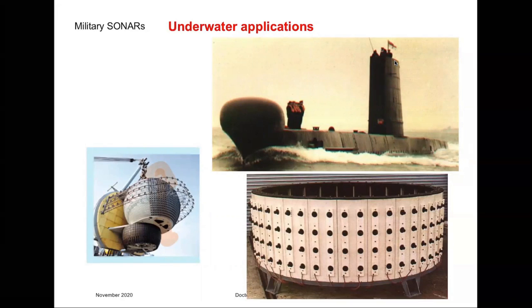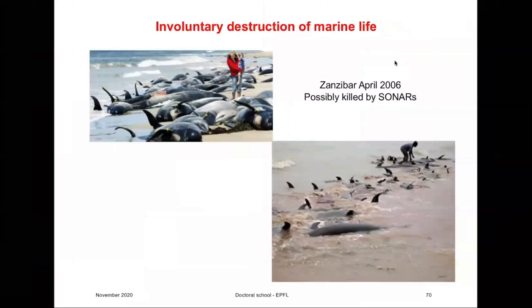As I said, several tens of tons of PZT. And one thing that can happen with these sonars is that the sound they produce can be huge. The sound intensity can be 120 or even more decibels. And if 120 decibels is a very large sound in air, you can imagine how much more powerful it is underwater.